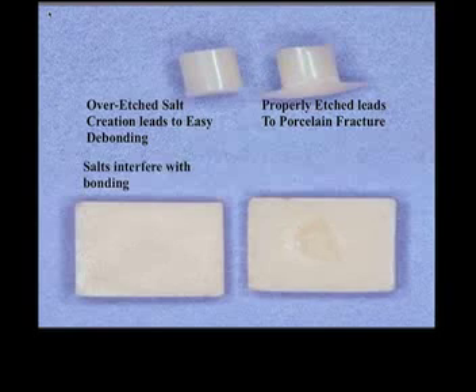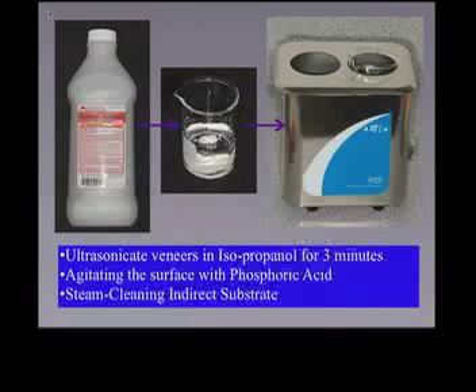Let's say we've over-etched. Well, the salts can be removed following a simple protocol of just rubbing alcohol. You ultrasonicate the veneers for 3 minutes, agitate the surface with phosphoric acid, and then steam clean it. The indirect substrate takes the salts right off, and then you would prime it again.